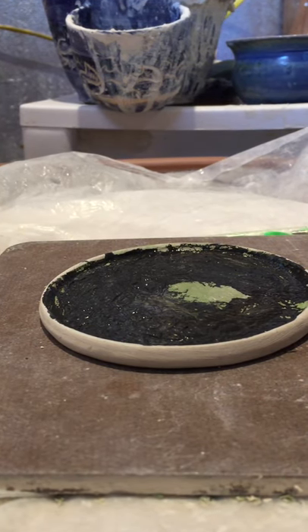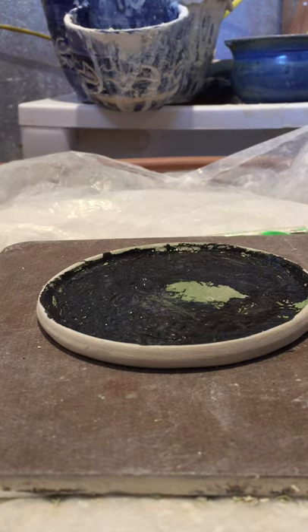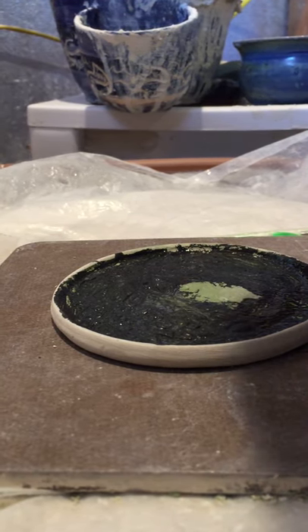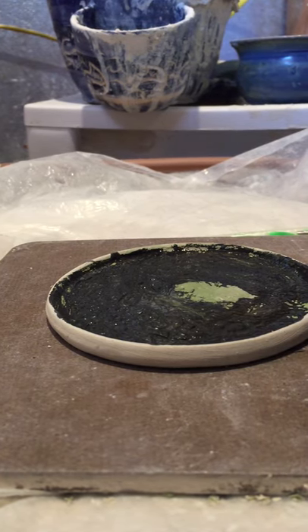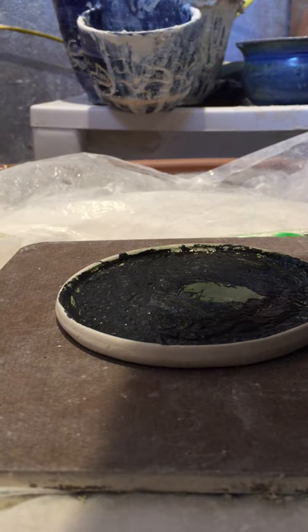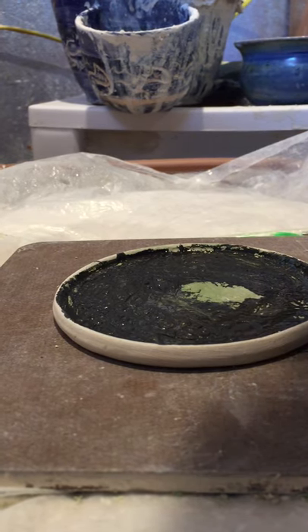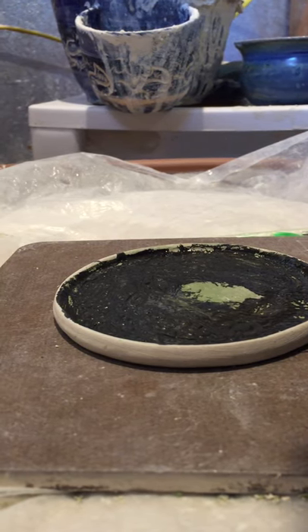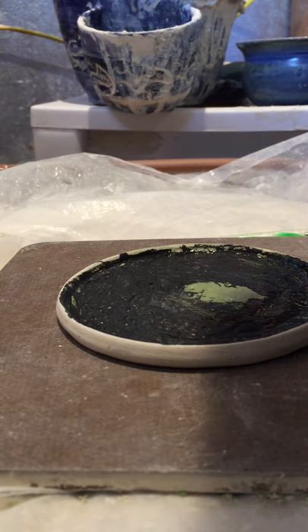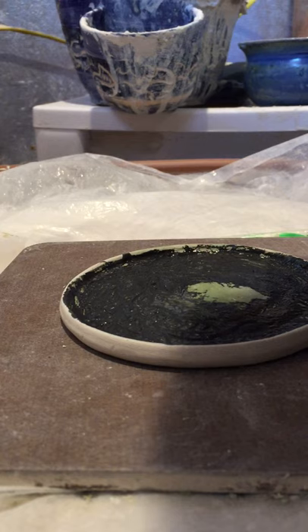That's all for right now — going to let that sit there for a few minutes. The underglaze doesn't have to be completely dry, but we don't want it real wet either; we kind of want it in-between. The reason I choose the velvet underglazes is they're good from the get-go, from the lowest cone temperatures up. I have fired it in Cone 10 when I was at the university, where we fired gas reduction kilns, and I had no problems with the velvet underglazes there either — you put them there, they stayed there.